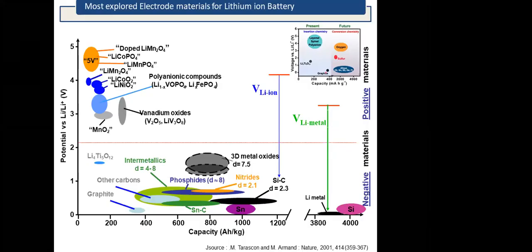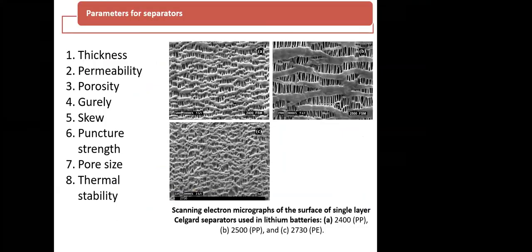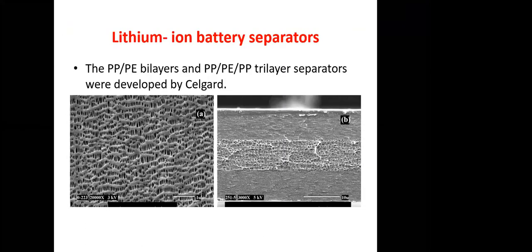So now, cathode, anode, and another thing is the separator. When we are talking about separator, we have to see the thickness, permeability, porosity, puncture strength, pore size, and thermal stability. Here you can see the scanning electron microscope images of Celgard 2400 separator. This separator is an insulating polymer like polypropylene or polyethylene, or a combination of polyethylene and polypropylene. Here you can see bilayer and trilayer structures of separator.